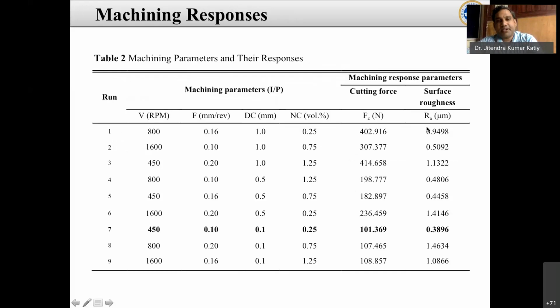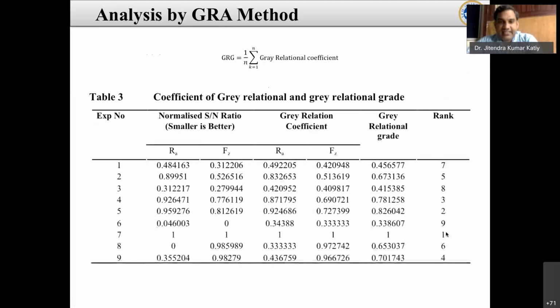These are the two machining response parameters: cutting forces and surface roughness. We made a Taguchi analysis with a total of 9 experiments. From all those 9 experiments, we observe that 450 RPM, 0.1 depth of cut, 0.1 mm per revolution feed, and 0.25 nanoparticle concentration give us lower forces, and the surface roughness is also lower. After that, we performed the grey relational analysis, calculated the grey relational coefficient by this formula, and ranked them from 1 to 9. Experiment 7 gives the most confident and most appropriate result compared to the others.